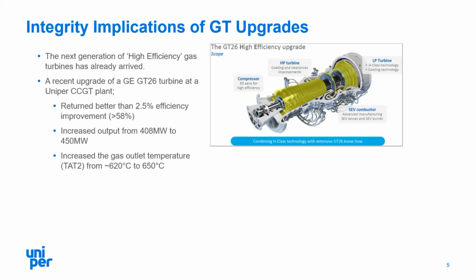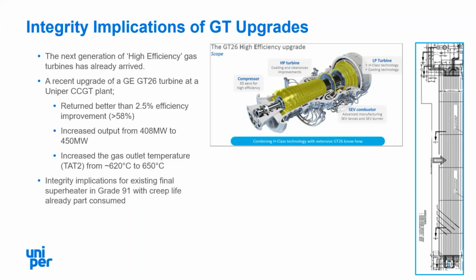Inevitably, there's always a downside to the plus. In this case, for the HRSG, it's an increase in the gas outlet temperature from approximately 620 degrees centigrade up to 650 degrees centigrade. So quite a pronounced increase. Going back to Jeff's presentation, for each 10-degree increase in metal temperature, you might expect a 50% reduction, or halving, of the creep life. So quite significant implications for the components.